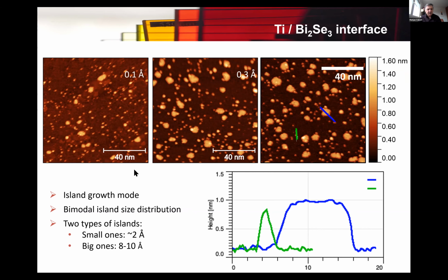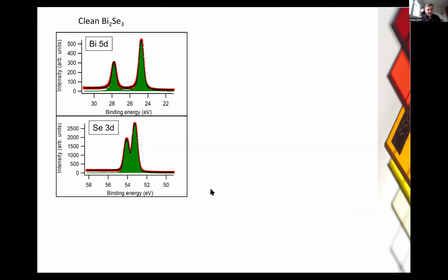So you see, these are now titanium spots, clusters that occur when you deposit the metal on the surface of bismuth selenide. So we analyzed the morphology. That's fine. But we also then started to study the interaction of this titanium with the surface of bismuth selenide.